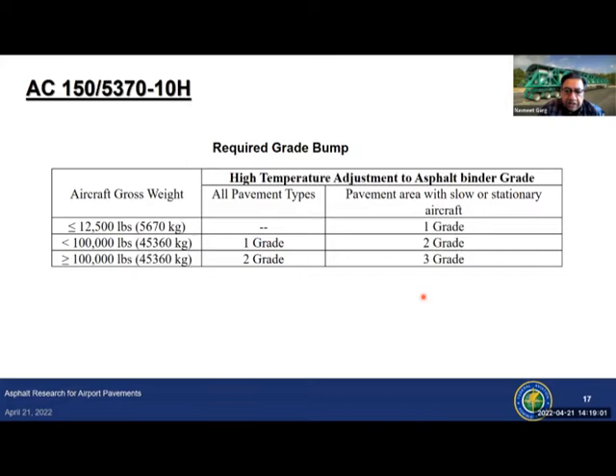It provides you criteria for selecting asphalt binder. So what it says is that you look at the location of the airport and see what is the base binder grade specified by your state DOT. And then depending on the maximum gross weight of the aircraft and the location of the pavement, whether it's an apron, taxiway, or runway, it provided guidance on how to bump the binder grades.